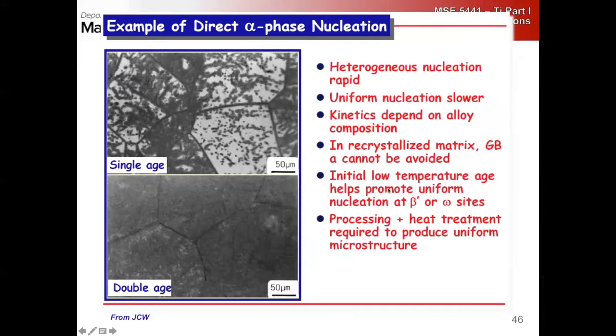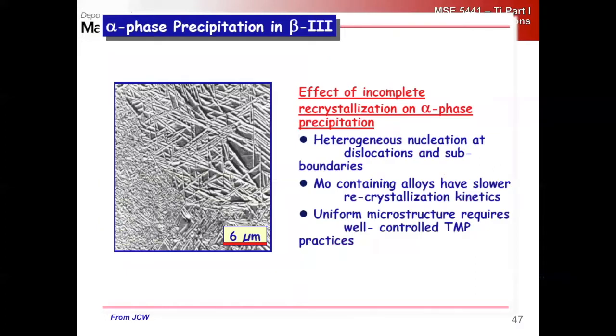But really, to get a really nice uniform distribution of alpha, we want to nucleate at the beta prime or omega sites. And that's what he's saying here by single age versus double age. So the single age was essentially direct nucleation of alpha at defects. The double age was nucleation of the omega or beta prime, and then aging. So we are working these, this is the beta worked.